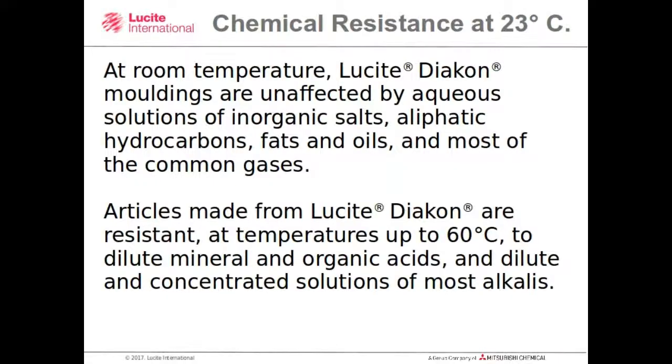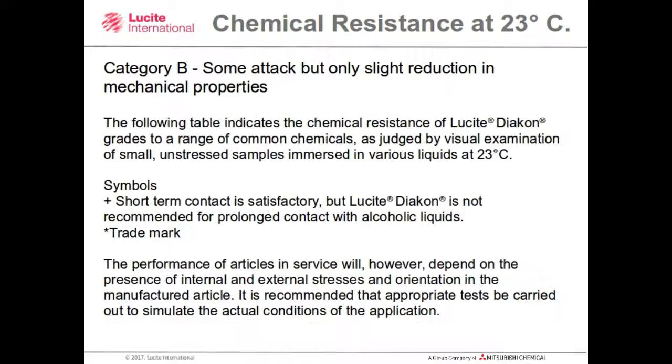At room temperature, Lucite Diakon mouldings are unaffected by aqueous solutions of inorganic salts, aliphatic hydrocarbons, fats and oils, and most of the common gases. Articles made from Lucite Diakon are resistant at temperatures up to 60 degrees centigrade to dilute mineral and organic acids and dilute and concentrated solutions of most alkalis.